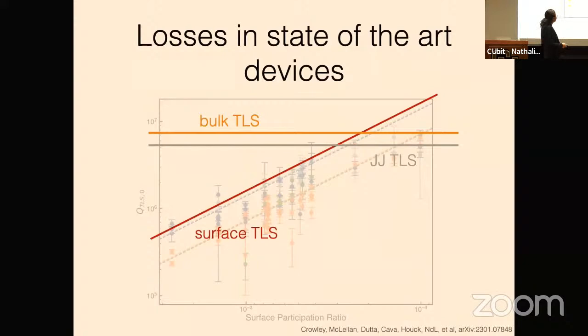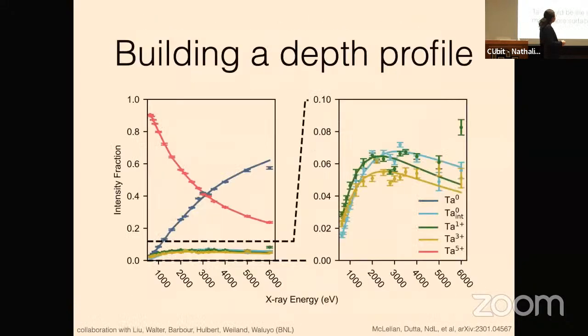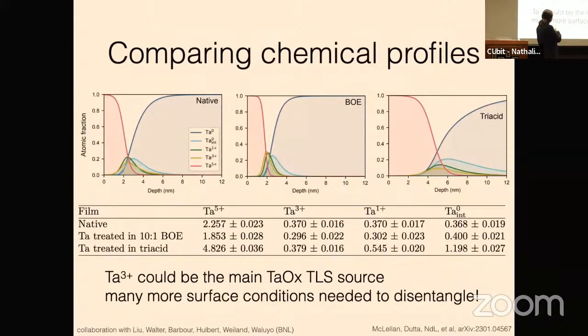So, in our depth profile, you can see that all the oxide is here, and then there's this interface layer that is maybe just a nanometer or something. And in niobium, on this scale, I think for many niobium devices, your oxide is out to like 10 nanometers, and then this suboxide interface layer is like another 10 nanometers. Okay, so it is drastically different. More of Nb2O5 and everything else? Yeah, that's right, and lots of different suboxides.